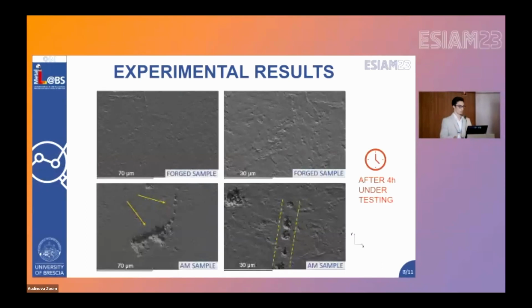So to look more in depth, we have performed electron microscopy analysis. And here I've shown just the more relevant one for time issue, and those are the ones after 4 hours under testing. You can see that in the top images, the surface of the first sample is just slightly corrugated and with some bit of erosion initiation.